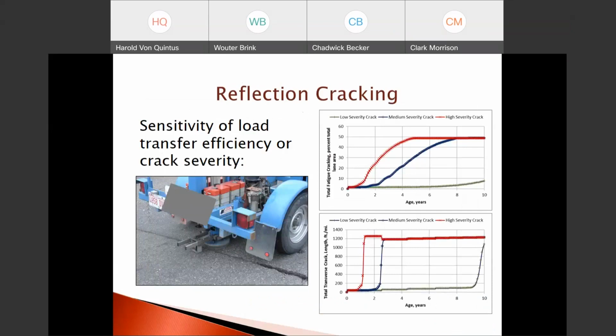Another very important parameter that we typically have ignored in the past is the load transfer efficiency. As I mentioned earlier, load transfer efficiency is tied to crack severity, at least from a global standpoint or global calibration, because load transfer efficiency was not measured within the LTPP program on flexible pavements, and that's the load transfer efficiency across transverse joints or cracks in the flexible pavement, as shown in the photo on this slide.